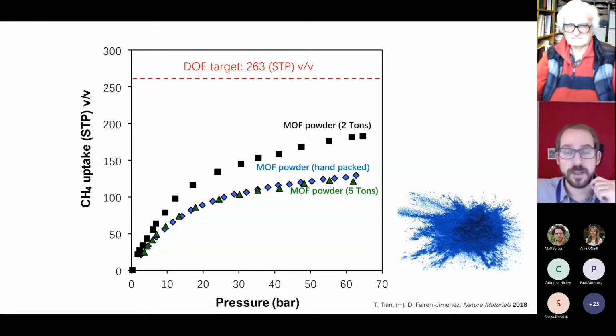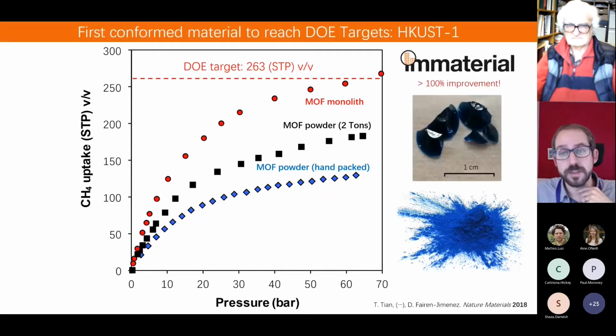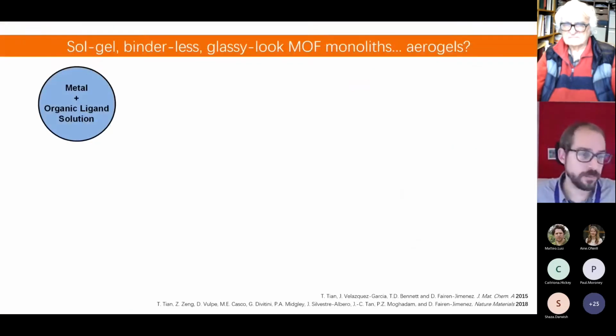The mechanical properties are not amazing. At 5 tons, you collapse part of the porosity of the structure. This is not good. In our case, the monolithic material was able to have a higher percentage improvement versus the powder, and we were able to reach the DOE target for the first time. So really happy, as I said, something we are exploiting with Immaterial.